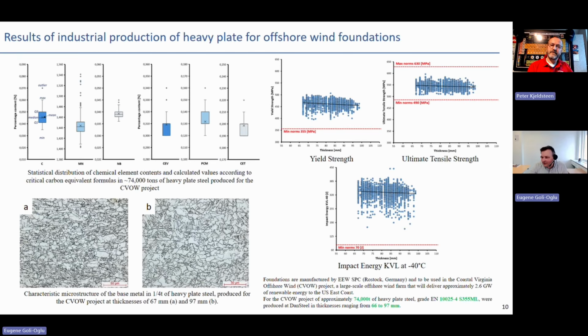Here is, for example, one picture where you see how steel looks in final condition using an optical microscope. In this case there are a lot of smaller grains, which give much more resistance to the steel against cracking, for example, because a crack needs to pass a much longer route if you have a lot of smaller grains compared to one big one.